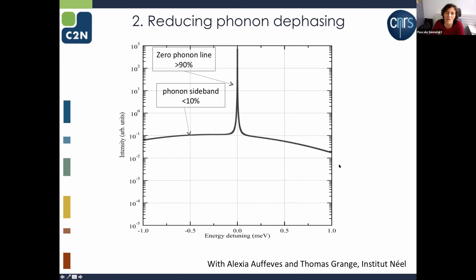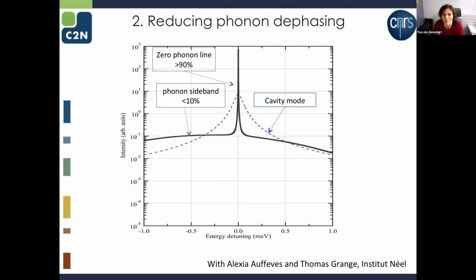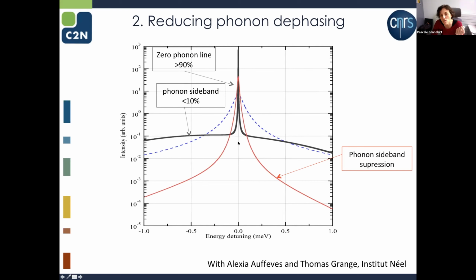You may have heard of them. For instance, for NV centers, this kind of phonon sideband is very big. For our quantum dot, it is not so big, just 10% of the emission at 10 Kelvin, but it's still too much to get highly indistinguishable photons. So what we have done is that when you put the quantum dot in a cavity and you accelerate the spontaneous emission, what we are actually doing is accelerating the emission of this line, not the rest of them. So the net result is that we end up with a much faster emission into the zero phonon line, the line that we want, and we suppress tremendously the emission in the phonon-assisted channels. And this is a very efficient way to gain in terms of purity of the state.